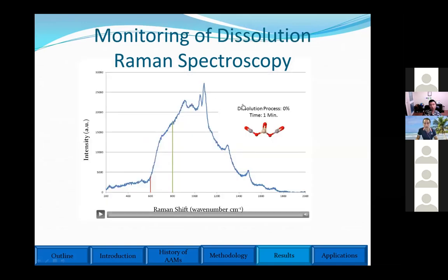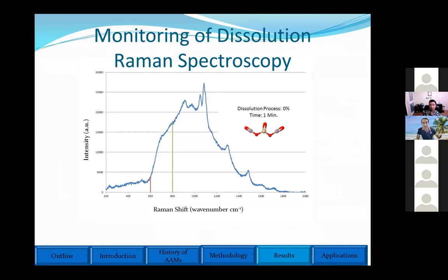And then I introduced chemical number 1, which was sodium hydroxide, into it, and monitored it. I set up the Raman spectroscopy device to get spectra after 1 minute, 1 minute, then 10 minutes, 10 minutes, half an hour, and 1 hour, 1 hour, for the whole 24 hours.